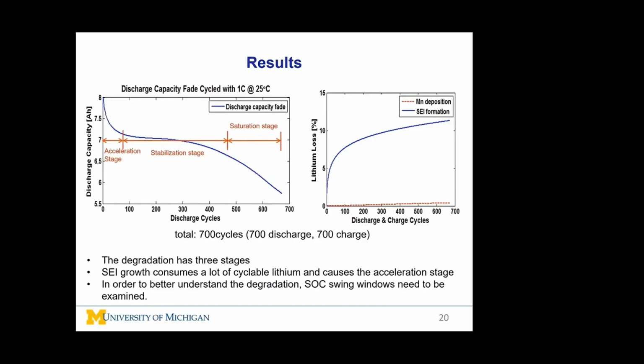The model revealed that degradation has three stages: the acceleration stage, stabilization stage, and saturation stage. SEI growth consumes a lot of cyclable lithium and causes the acceleration stage. As the SEI layer grows thicker, SEI formation on the anode surface slows down, and the battery enters the stabilization stage.